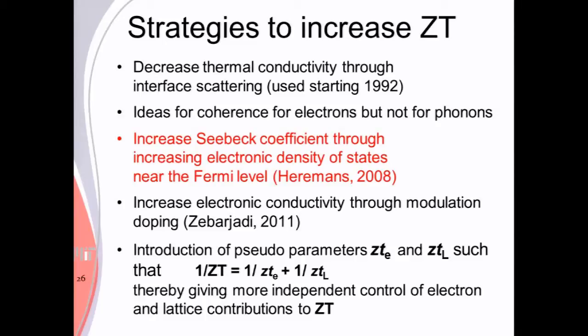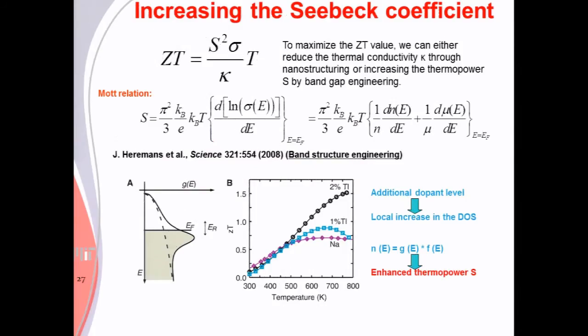The next thing was the density of states idea. This is Jos Heremans' idea, and when this paper came out, many people were very excited about it. Instead of the very simple kind of density of states that we write about with a simple exponential factor, we have a bump. We have some kind of impurity that's causing a singularity in the density of states. If your Fermi level is quite close to that, you have some way to vary what's happening and perhaps differentiate between electron and phonon scattering.